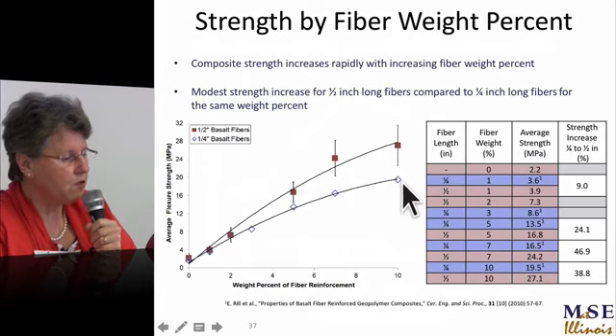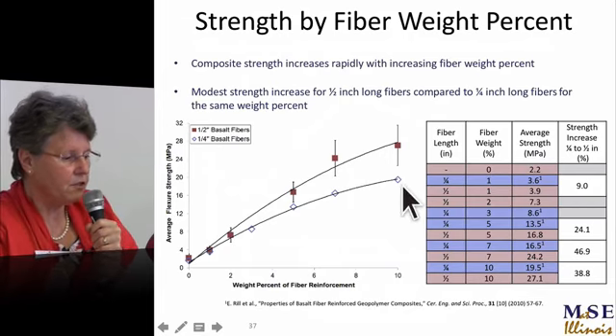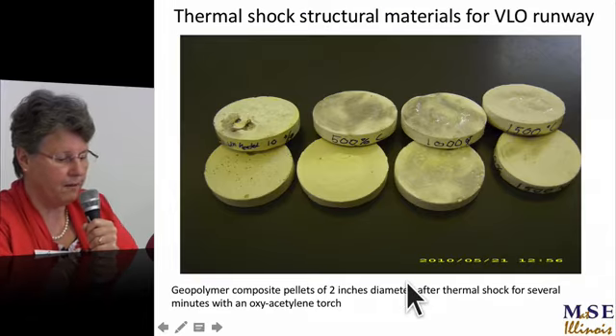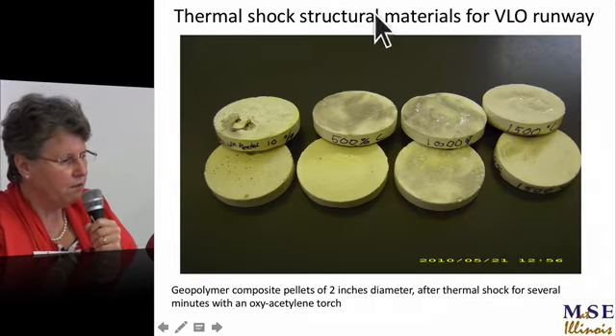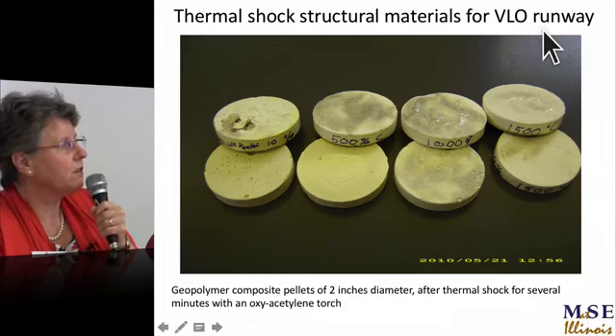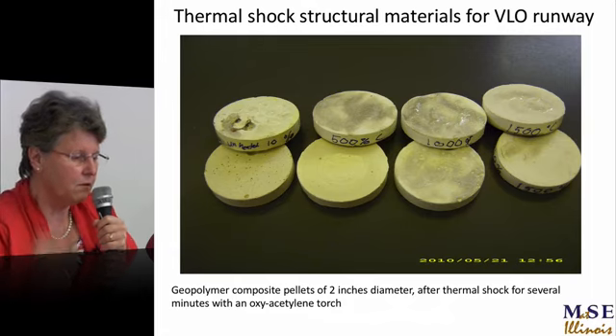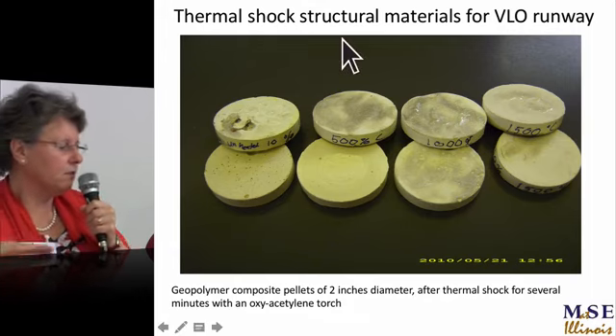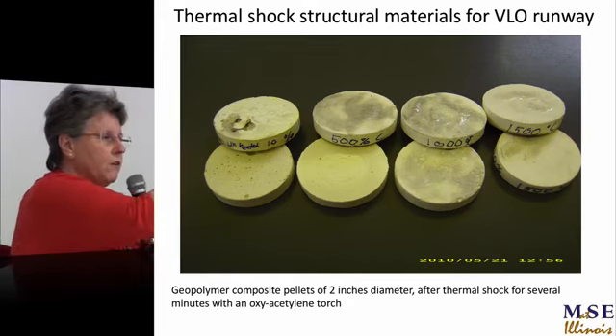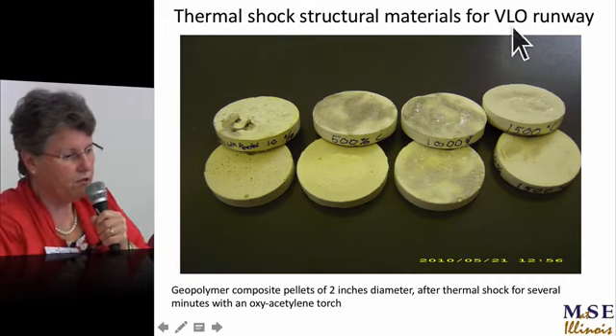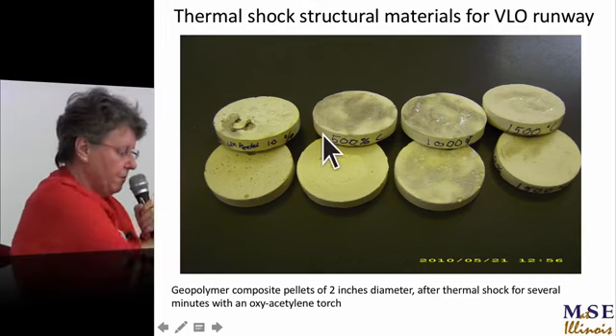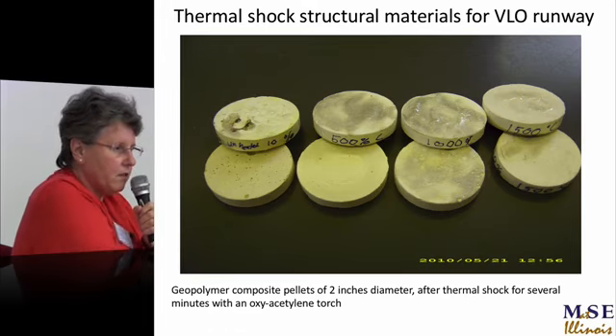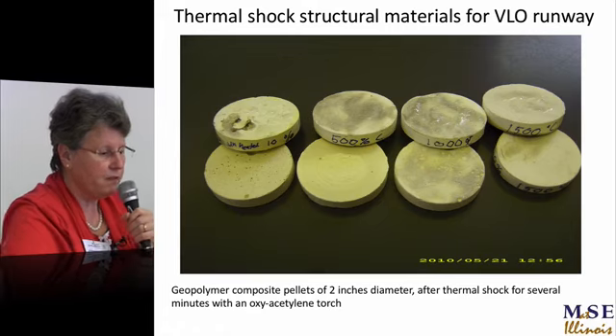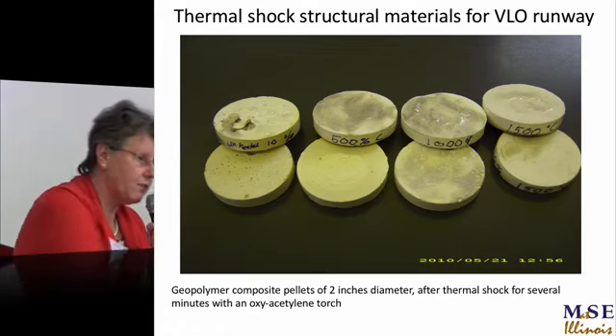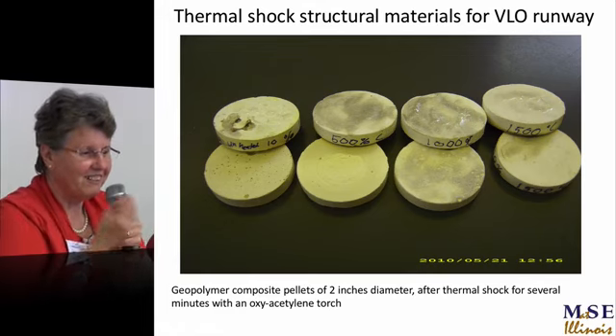Here you can throw in basalt chopped fibres, a quarter inch or a half inch. You can get 17 megapascals or 27 megapascals just with 10 weight% basalt chopped fibres. This was for a vertical lift-off runway. The Air Force at Tyndall Air Force Base wanted it because the aeroplanes don't just run off like that, they take off like a rocket and then they go somewhere. That's called a vertical lift-off, and when they take off they burn the cement and little rocks hit the aeroplane. And at Edwards Air Force Base in California, as soon as one of them takes off, you have to go out and vacuum the runway to clean up the little rocks.